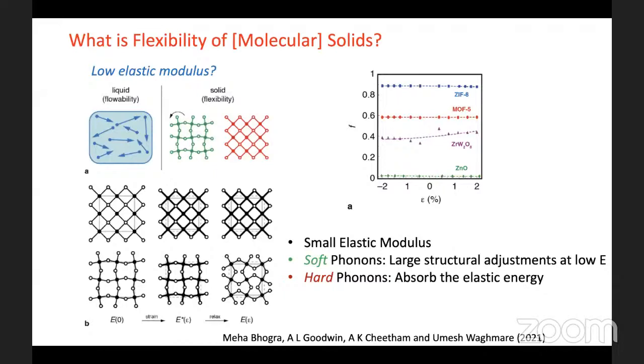Earlier, people used to believe that high flexibility is associated with small elastic modulus, like a soft material or a molecular material. What we show is, well, softness is important in accommodating large structural adjustments at low energy cost, but hard phonons are also very crucial in absorbing the elastic energy and retaining the structure. So this is the new insight we have obtained from this analysis.